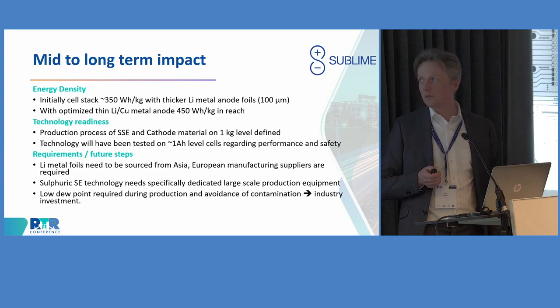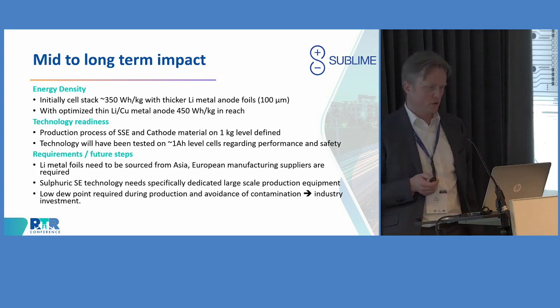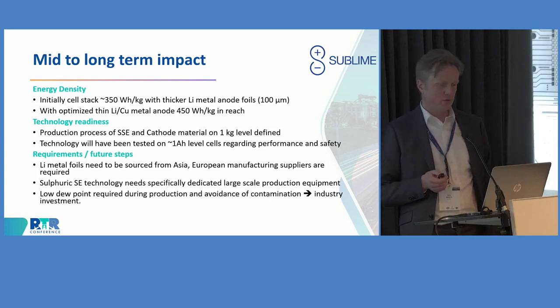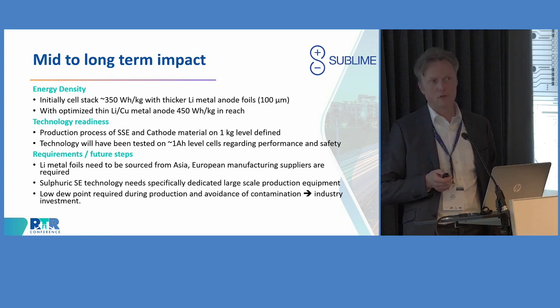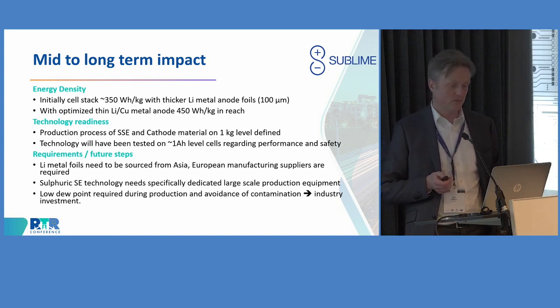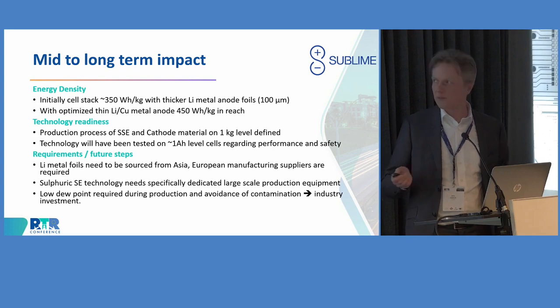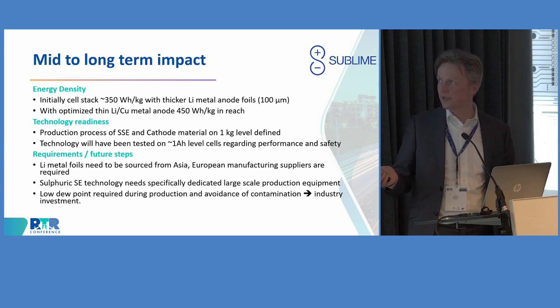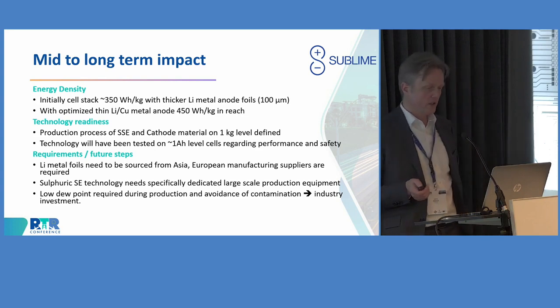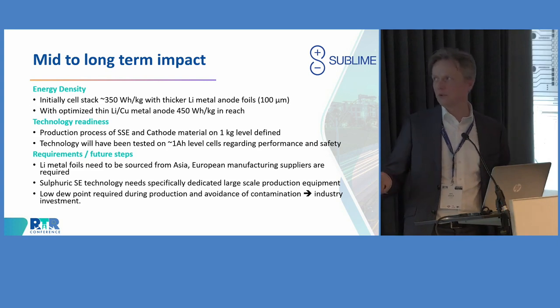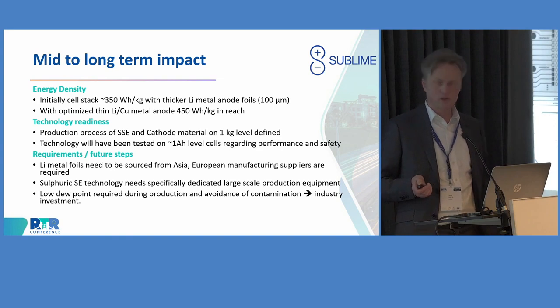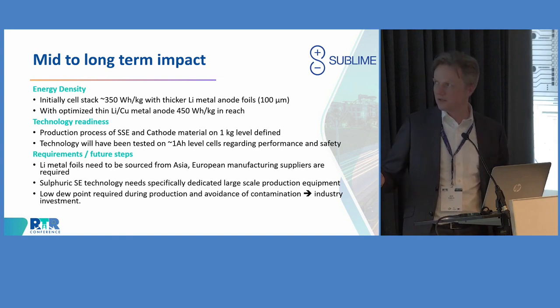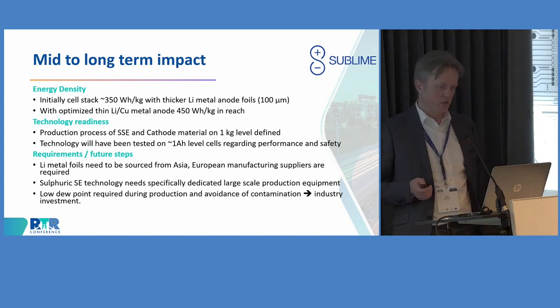Now, I would like to come basically to the conclusions of this project. We see in terms of the mid to long term impacts, we think that of course we have some problems in order to source the correct material for the anode side at the moment. So we have to use the thicker material for the lithium. That would mean that we would target then with that material only first a lower energy density, and once we have resolved the problems, then with the thinner and the optimized lithium copper metal anode again, we would be able then to reach the high energy capacity.